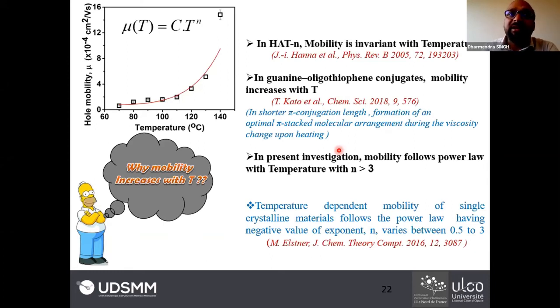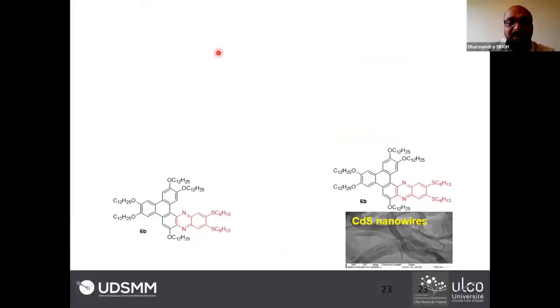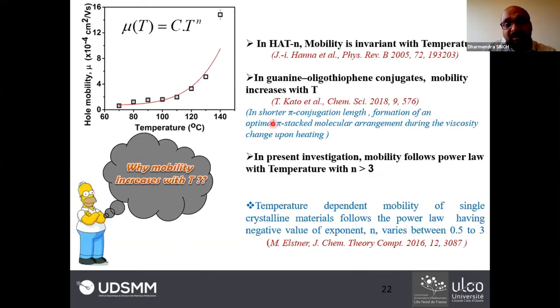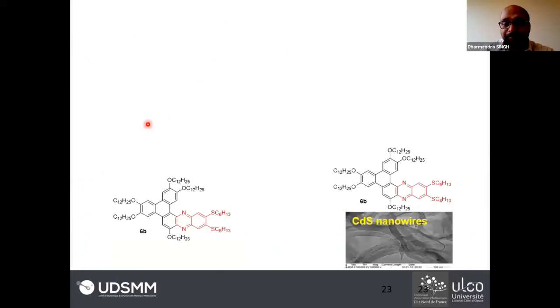So this means mobility doesn't vary with temperature within a particular mesophase width. That's why here we have estimated the hole mobility as a function of temperature, and we found that the hole mobility increases with respect to temperature. This is the first time we have recorded this nature, and we found that when our molecules behave with growth of domains like single crystals, this nature is possible due to that mechanism.